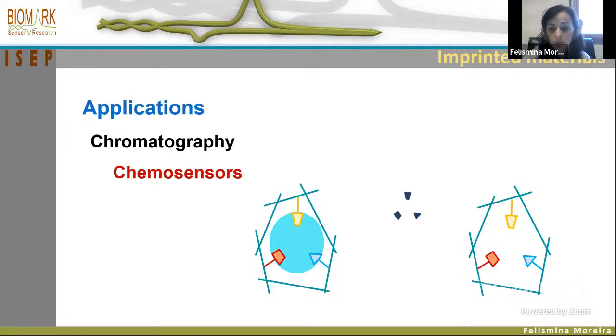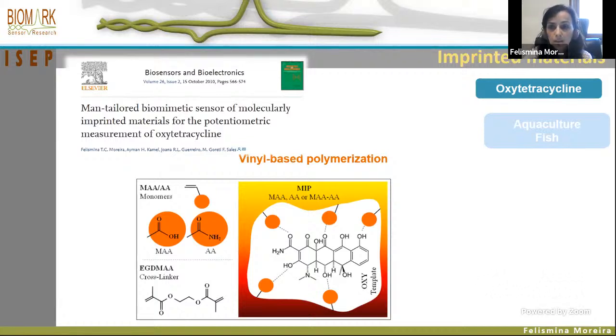The biomimetic materials, or plastic antibodies, are widely used in chromatography or could be used in chemosensors. One example of a biomimetic material synthesized to detect an antimicrobial, oxytetracycline, widely used in aquaculture, was the following. We synthesized one plastic antibody by mixing the functional monomers, in this case methacrylic acid and acrylamide, and one cross-linker, ethylene glycol dimethacrylate. We dissolve these compounds with the target analyte in one organic solvent, add the initiator, in this case benzoyl peroxide, and submit the solution to a heating process for 30 minutes at 80 degrees.